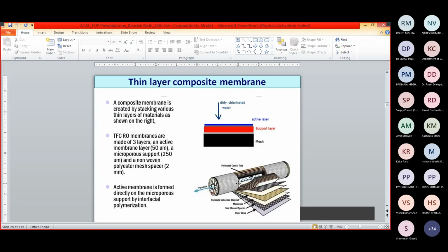Now, you might have heard this name, TFC. We call it thin film composite membrane. Nowadays composite membranes are widely used, because a composite membrane has good mechanical strength and also good permeation property. So you have to select which type of active layer is used. A composite membrane is created by stacking various thin layers of material one after another: an active layer, then a support layer, then another mesh. TFC thin film composite RO membranes are made of 3 layers: an active membrane layer around 50 micrometer thick, then a microporous support layer around 250 micrometer, and then a non-woven polyester mesh spacer of 2 mm.